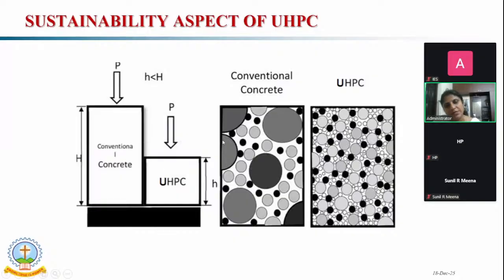By comparing conventional concrete and UHPC, as I said earlier, the particle packing is too good. It has minimum pores in the case of UHPC. By minimizing the pores, the particle packing density can be improved. By improving the particle packing density, we can enhance all the mechanical characteristics as well as the durability properties. Also, we can reduce the depth of the section. That means we can introduce a slender cross section.